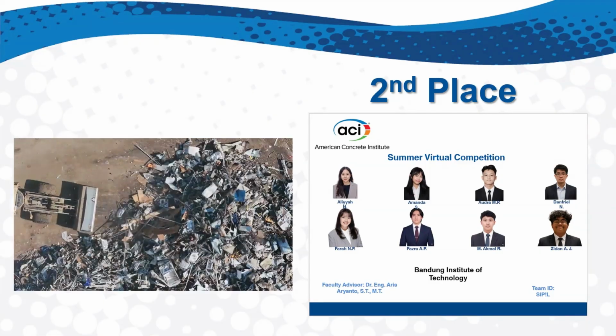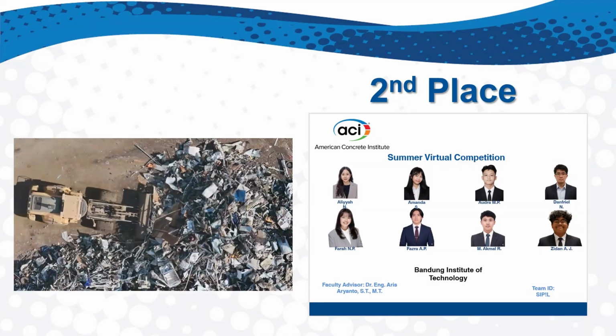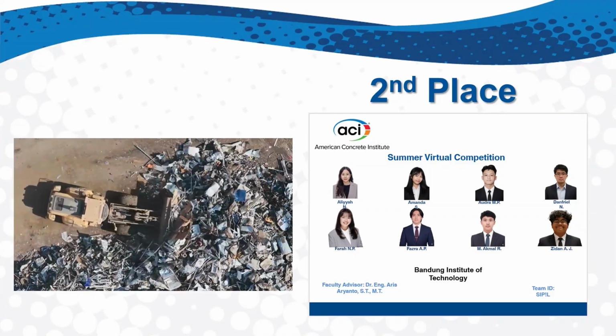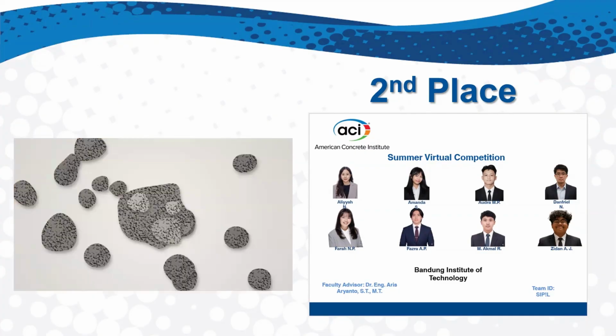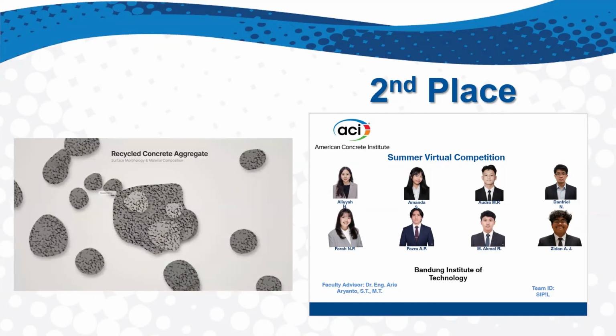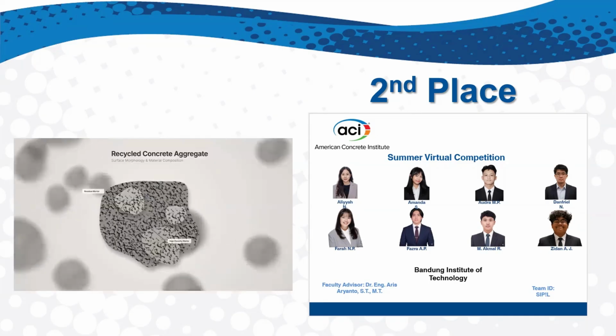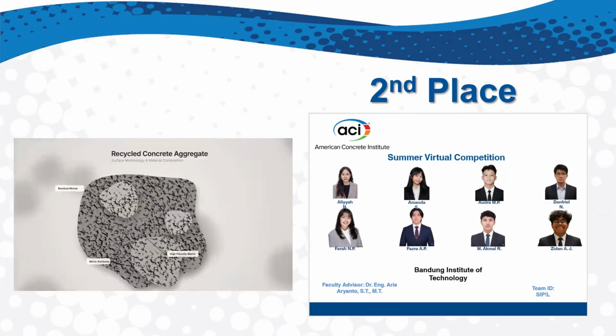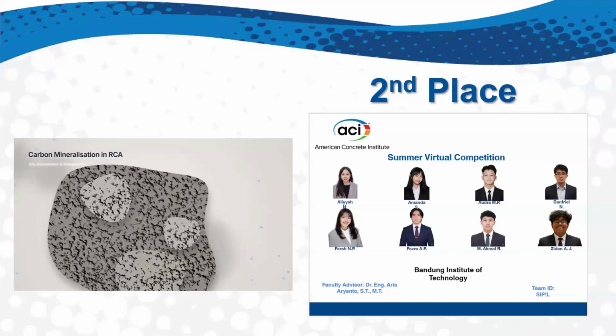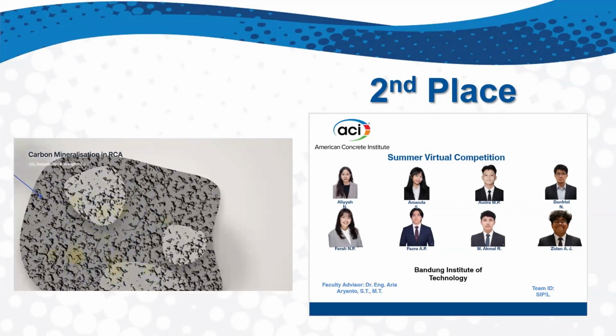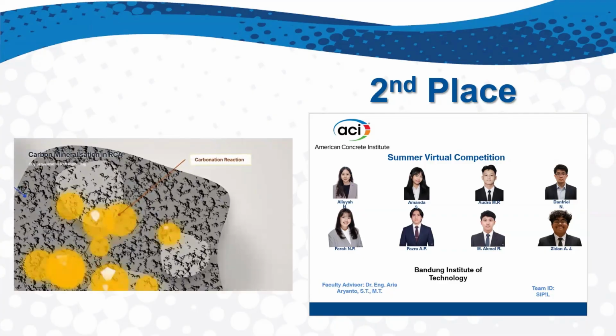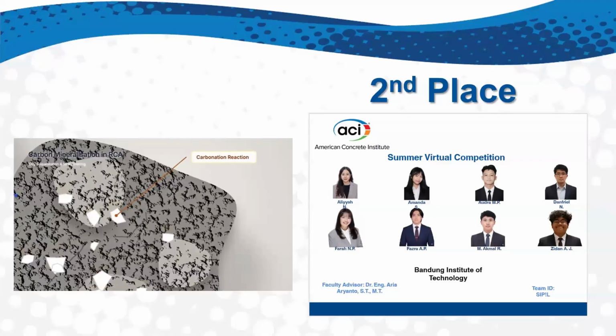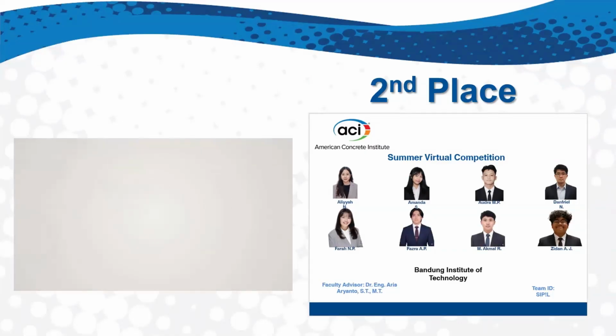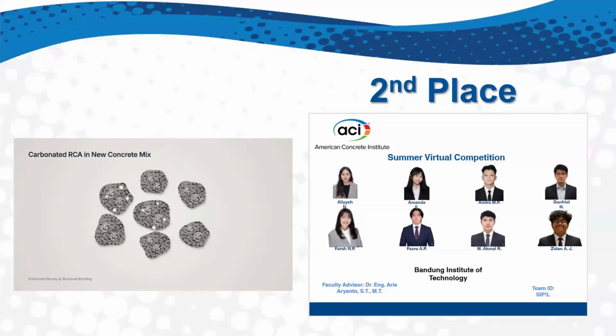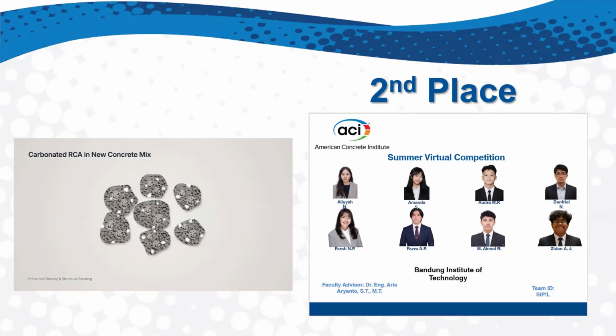Our innovation takes this natural reaction and engineers it across 3 strategic injection points. Phase 1 is recovery and preparation. Rubble is crushed, cleaned, and graded, so the old mortar on RCA is exposed and ready to react. Phase 2, carbon dioxide curing. In a controlled chamber or curing environment, carbon dioxide diffuses into that mortar and forms calcium carbonate inside the pores. Phase 3 is reuse. The carbonated RCA returns to new concrete with lower porosity and stronger bonding potential. After its service life ends, the cycle can begin again.